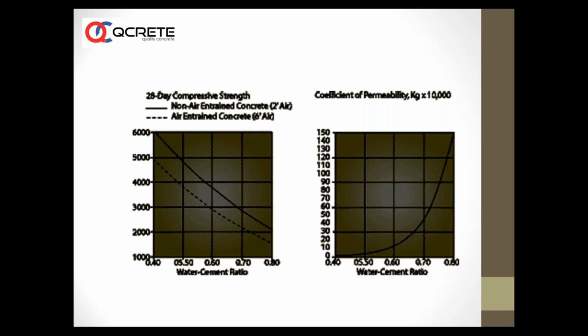That is why when specifying durable concrete, HPC, etc., people go for specifying below 0.4. Even in case of extreme exposure, meaning when concrete structures are exposed to marine atmosphere or severe exposure conditions where chlorides and sulfates are more, or even liquid containing or water retaining structures, the specification says you need to keep the water cement ratio lesser than or equal to 0.4. So these two graphs we need to remember, as they govern the quality of concrete that we produce.